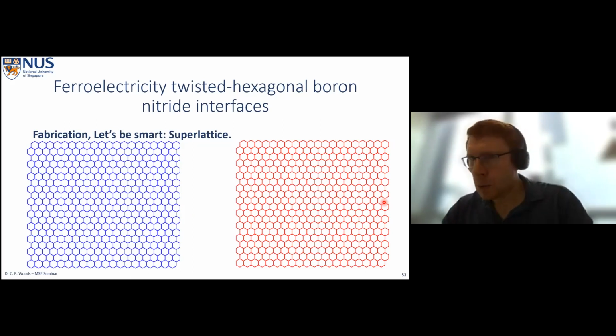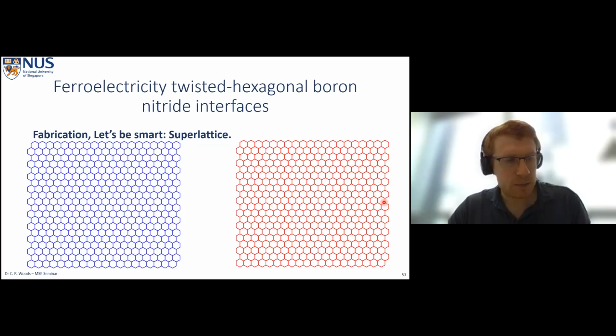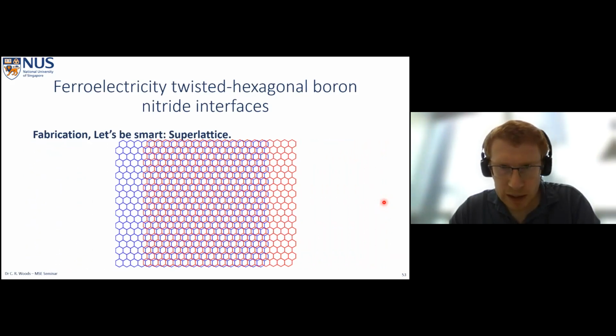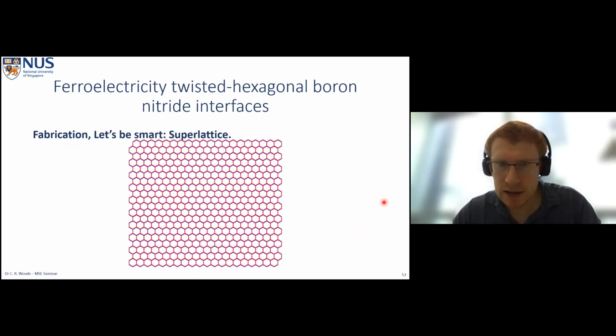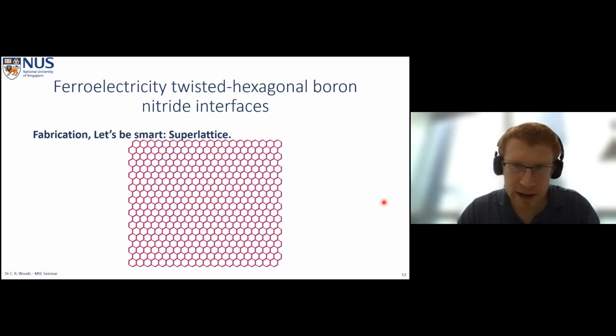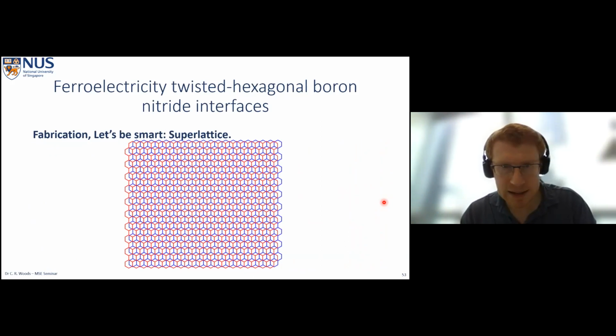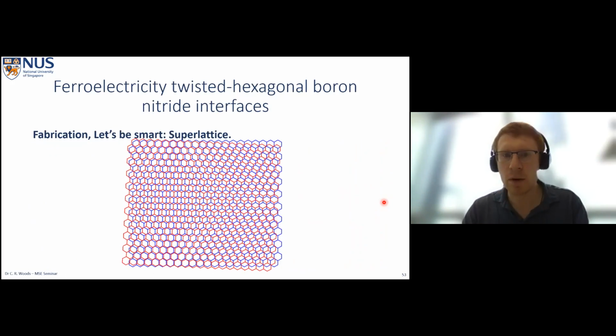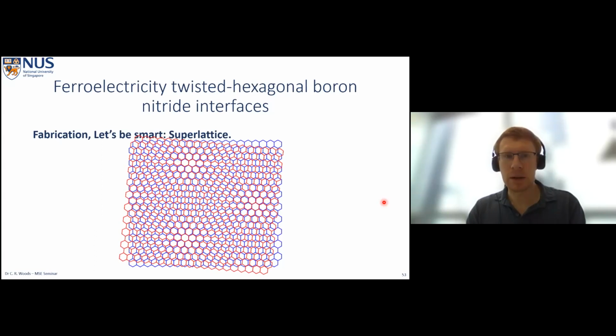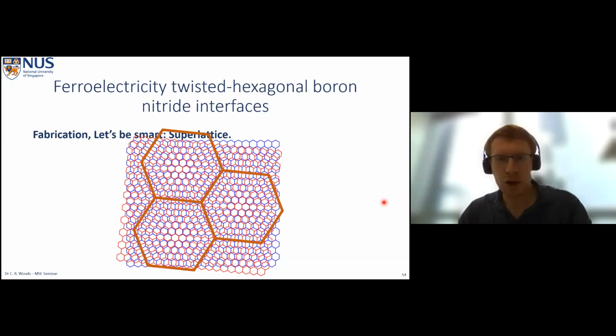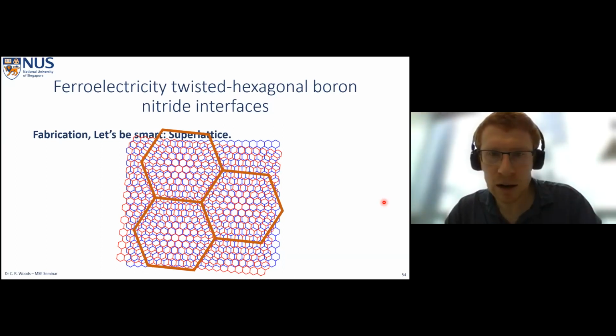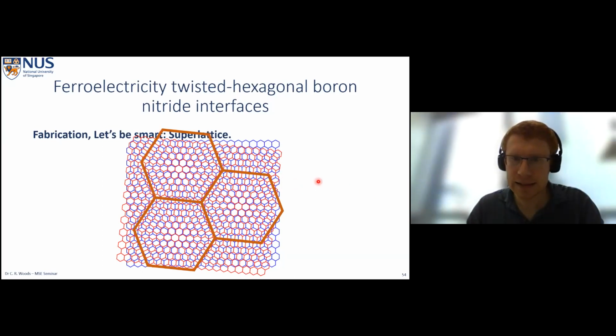Okay, so now if we want to investigate these different stacking configurations in our samples, we have to be a little bit smart about the way that we do it. So we could put two boron nitrides on top of each other and try and see something like this. This would correspond to like AA stacking, where the hexagons sit perfectly on top of each other. And then we could try and translate it by one bond length to create AB stacking. But actually a much smarter thing to do would just be to add a small twist angle to one of the boron nitrides. And then we'll create something called a moire pattern between the two of them, or a super lattice. And hopefully you can see that there is a new, much larger periodicity in this image, which I highlight with these brown hexagons here.